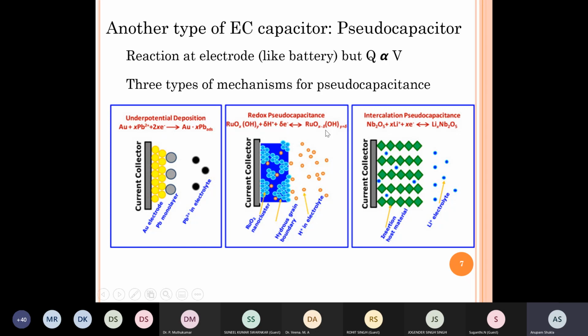When these processes occur on the surface of the electrode, they are fast enough that they behave like a capacitor. A battery has a slow response because the reaction occurs inside the electrode, and then it is limited by the speed at which the reacting species can move into the porous solid structure. The only difference here is that the reaction is confined to the surface. When that happens, because of some things that we are not putting here mathematically, it turns out that the charge stored, which is related to the amount of reaction that has occurred, depends on the potential.